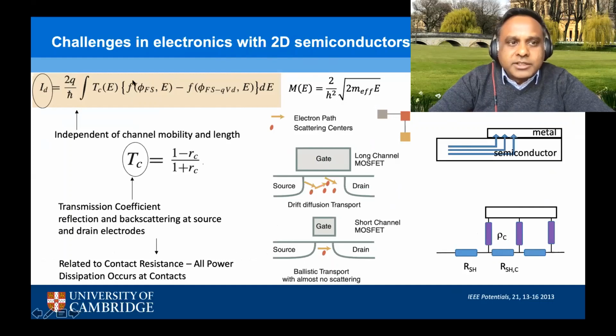An additional parameter that one has to consider when one looks at these very short channel devices with 2D semiconductors is that when you go down to sub 10 nanometers, the operation of the device is closer to ballistic transport, where there's no scattering in the channel, in contrast to long channel devices. And so if you work out the expression for the drain current in a ballistic transistor, one can see that it's primarily influenced by this parameter TC, the transmission coefficient, and the transmission coefficient is related to these parameters, primarily this RC. And RC is the contact resistance, due to reflection and backscattering at the source and drain electrodes.